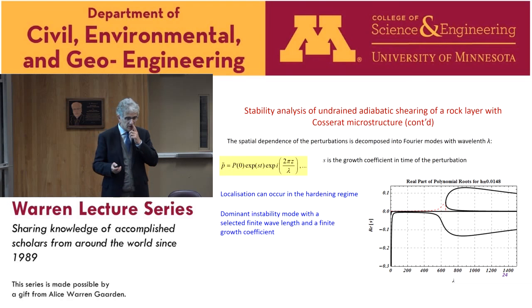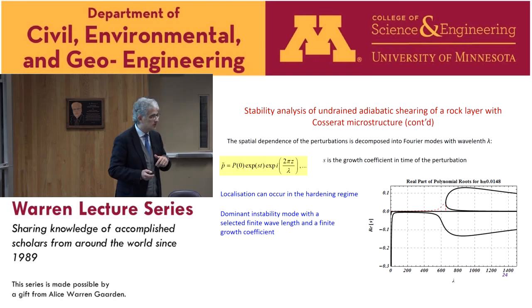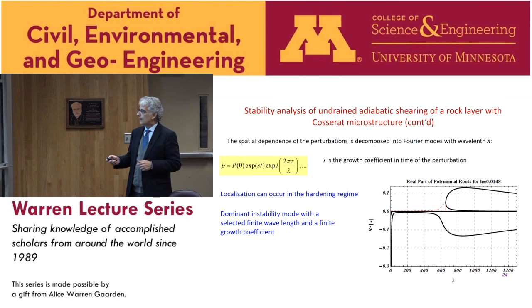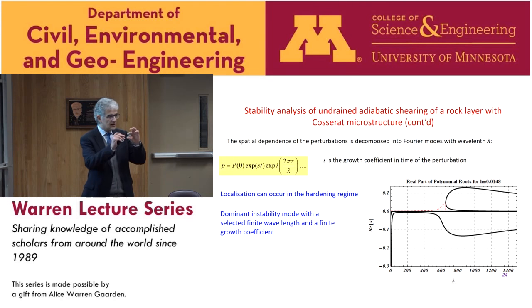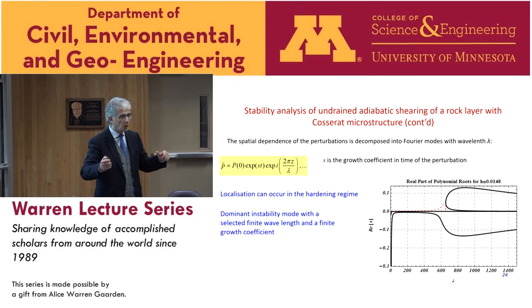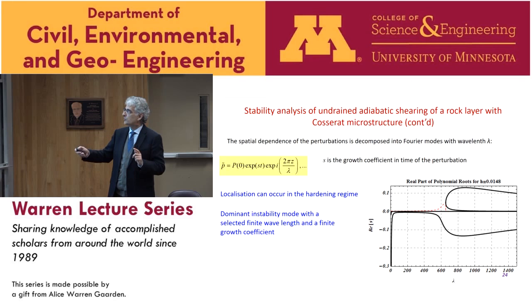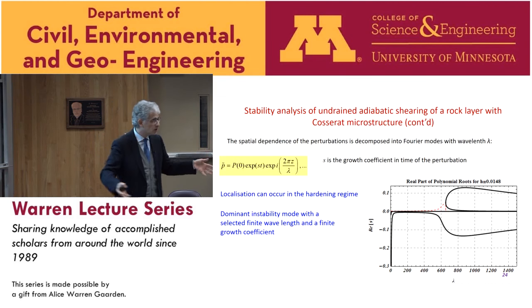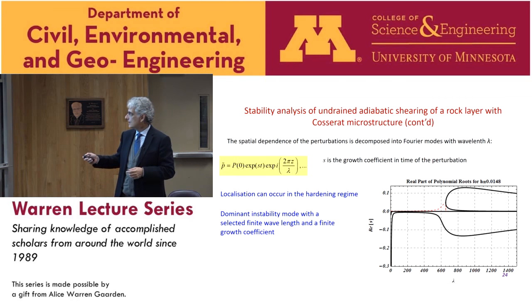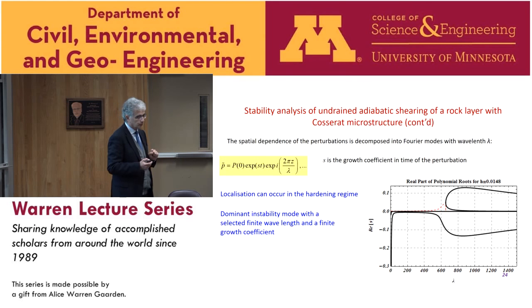And the other interesting result, related to the introduction of Cosserat terms and the fully dynamic analysis, is that looking at all possible perturbations at the instability, all perturbations with a wavelength smaller than some critical value are actually stable. It means that if the layer is thin enough, it will remain stable. Only the wavelengths which are bigger have a growth coefficient which is positive but finite, and we have here a maximum indicating that there is one particular mode which will develop faster than the others. So we will relate this to the actual thickness of the localized mode. I have no time to show all the details of this comparison, but I will show later on some numerical results that address this problem.